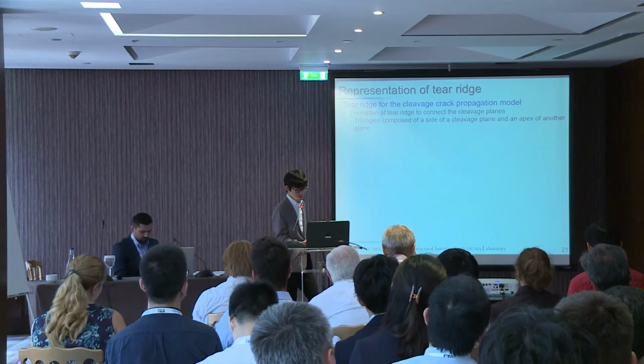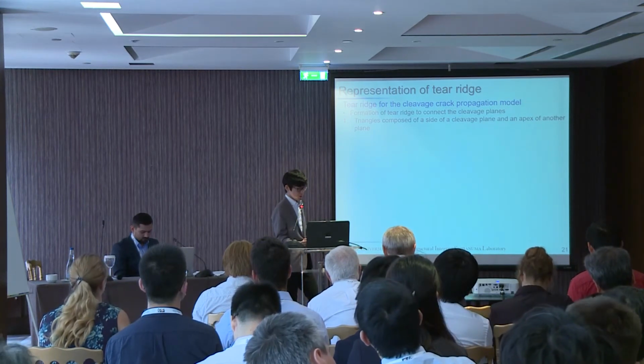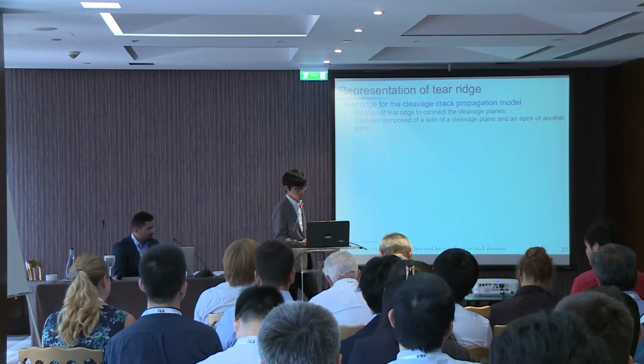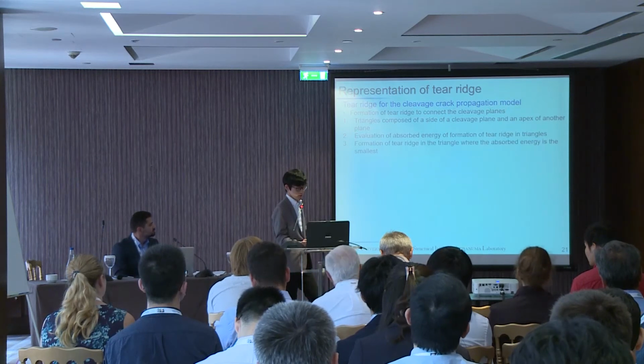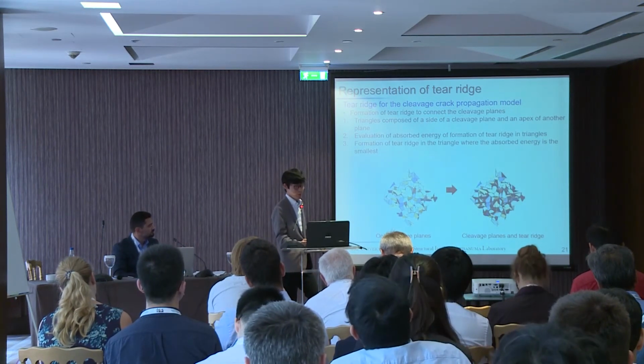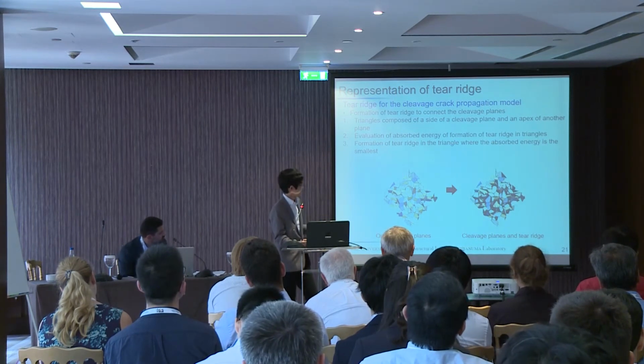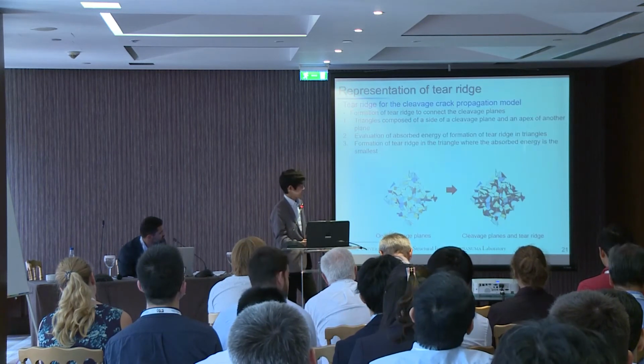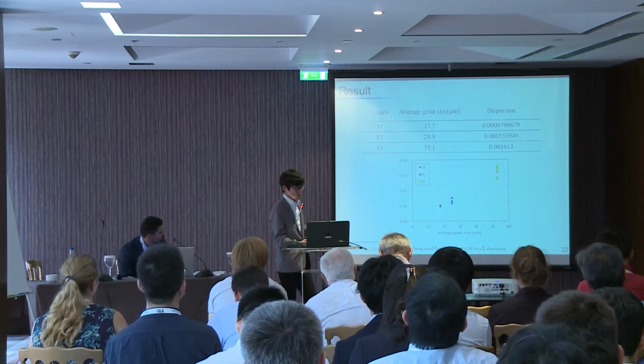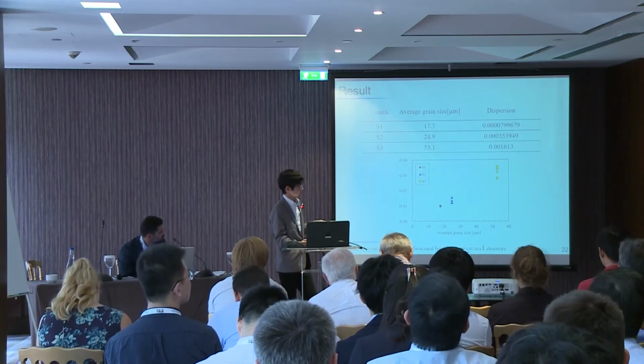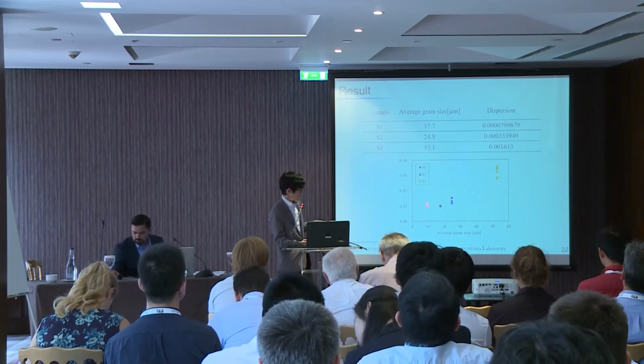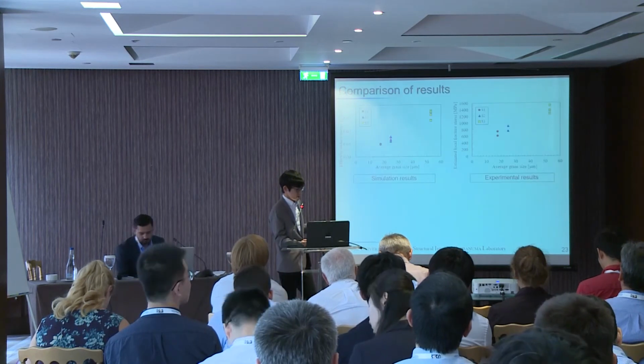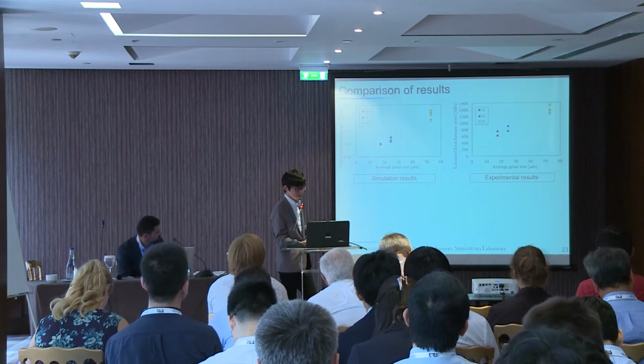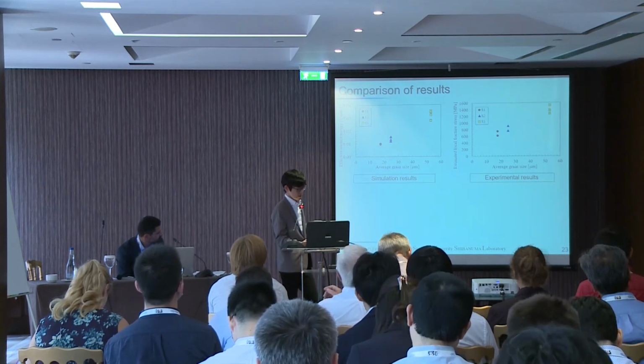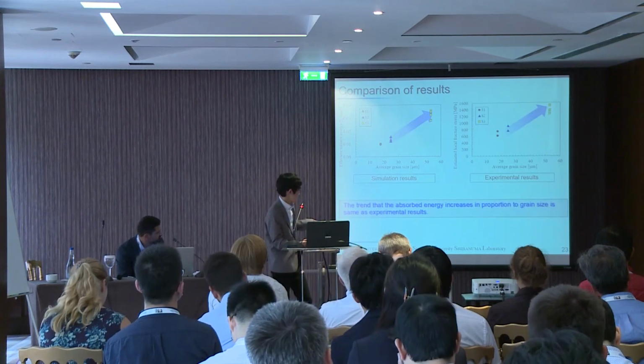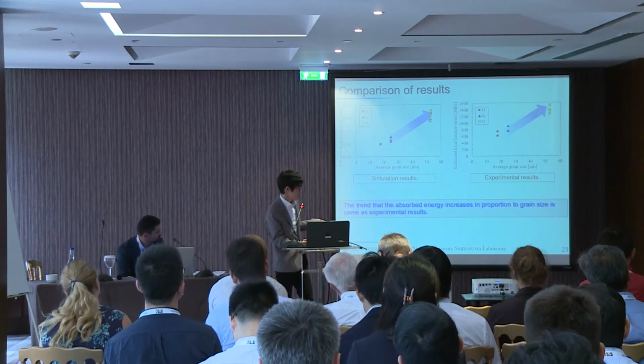And we explained the method of cleavage formation. We don't have enough time, so this black part is cleavage. And this is input data to simulate grain distribution by Neper. And the result of the absorbed energy is this. And we compared simulation results and experimental results. Both results have the trend that the absorbed energy increases in proportion to grain size.